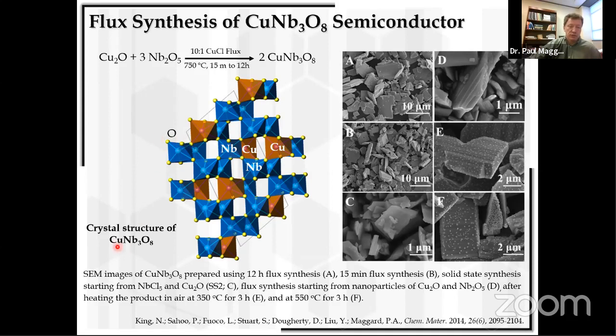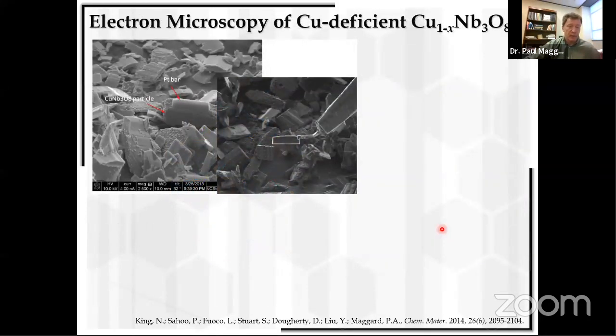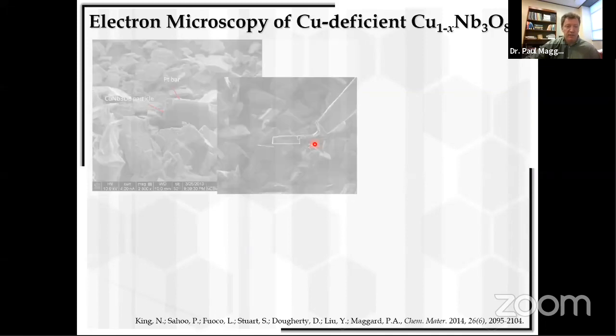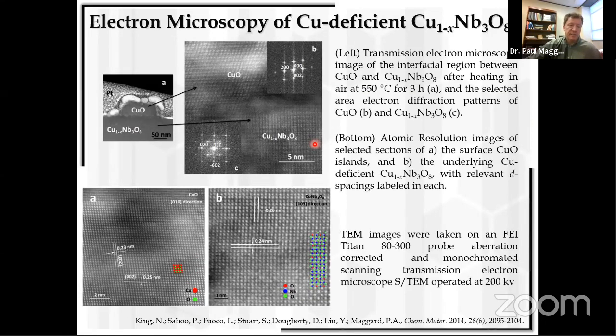And so here's the crystalline structure of the 138 phase. And again, we can make it by flux synthesis and heat them in air. And you can see those particles, once you heat them in air, compared to before you heated them, they look like they have chicken pox on them or smallpox or something, because those little islands come out at the surfaces, okay, which makes them highly active particles for water reduction. We've imaged many of these, for example, using FIB to slice out small sections of them and picking them up and imaging them. And we can easily see we have little copper oxide islands at the surface.